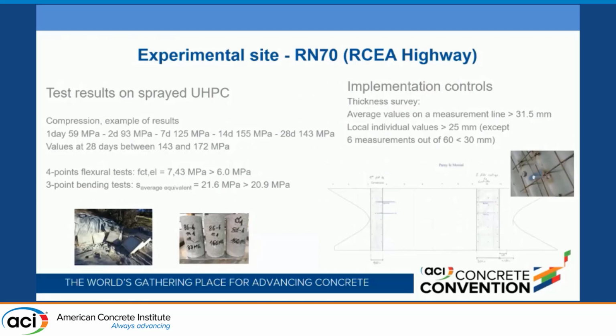The average value on measurements was over 31.5 millimeters. All individual values were above 25 millimeters, and only 6 out of 60 measuring points were between 25 and 30 millimeters.